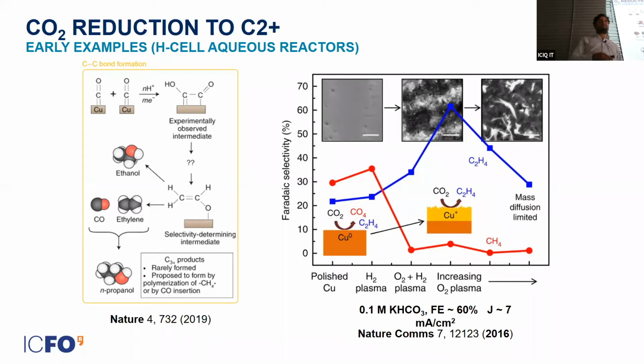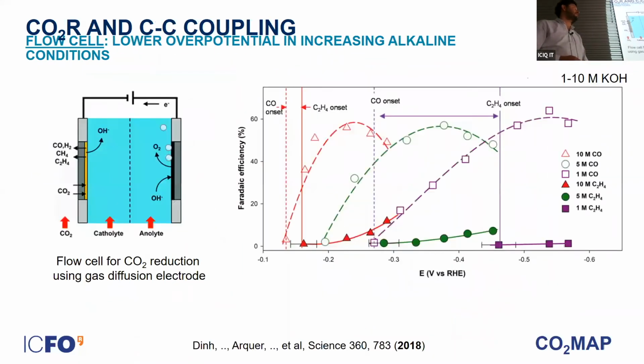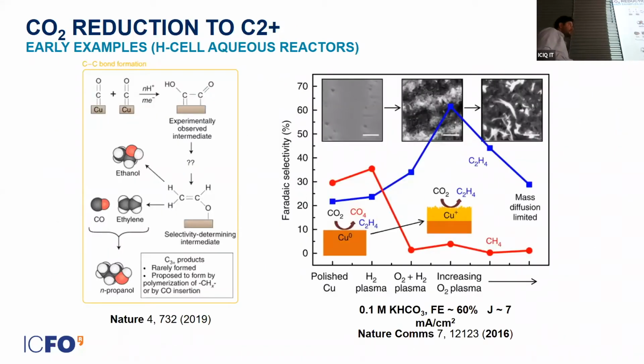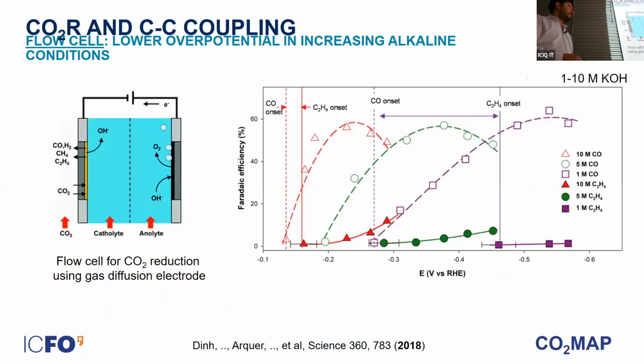So all the catalysts were embedded in the electrolyte, and I'll show you why this is important. It's important because in part the current density, I forgot to add the units here, sorry. So this is the partial current density for ethylene here, only 7 milliamps per square centimeter. And this is kind of far from the numbers that you would need to achieve to be competitive from the techno-economic point of view. So in order for this process to be interesting, you would need to have currents on the order of hundreds of milliamps. So this is still far. Nevertheless, it's a good beginning. Now you can achieve selective ethylene generation.